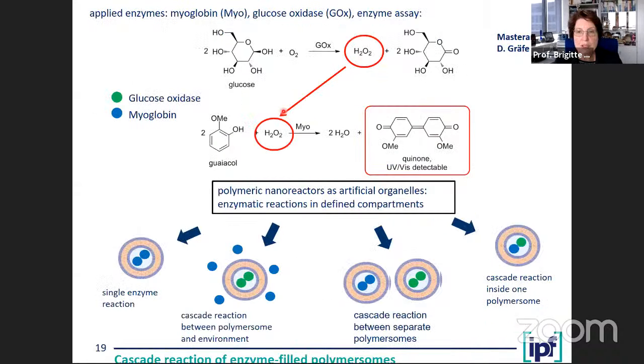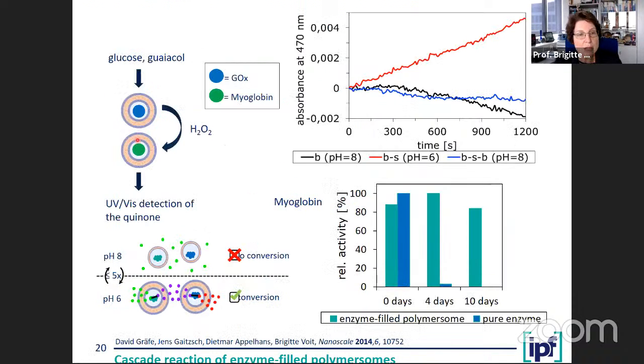You can do this also for various types of reaction. We also made cascade reactions using two enzymes: glucose oxidase, which produces peroxide, and this peroxide is then converted with myoglobin into the colored product. And we looked at how we can do it with the different encapsulated enzymes. I just want to show you that it works also well when you individually encapsulate the enzymes and allow a cascade reaction. First, you have a diffusion into one nanoreactor, product is formed, the product then diffuses into the other nanoreactor and produces the final product. And it works again very well, pH dependent.